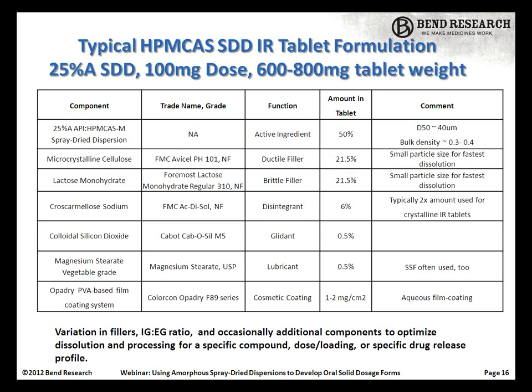We usually use a mixture of a ductile and a brittle filler. There are some exceptions to that, but it is the most common here. One thing we find is that generally we'll get better performance by using the smaller grades of these. Again, this is trying to maximize the surface area of the excipients relative to the spray-dried dispersion. We're trying to minimize the spray-dried dispersion particle interfaces within the tablet. So small particle size fillers generally is better, especially if we're dry granulating. That generally is not a big issue.